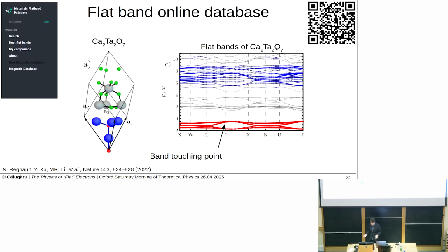And this, once again, is not just a mathematical toy model. You can actually go ahead and apply this to real crystals, and we've actually done that. I'm highlighting here one of the compounds that shows a flat band with a band touching point that can be diagnosed with this type of prescription. Actually, if you want, you can go ahead and scan this QR code, and it points to an online database of flat bands, and in your spare time, you might want to synthesize one of those compounds.